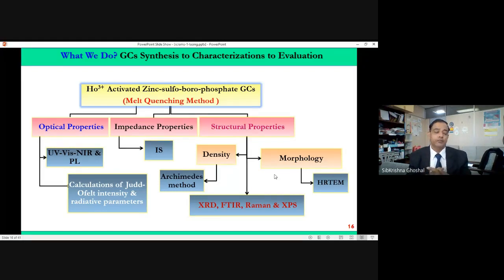So what characterization do we do on this kind of material? We do ultraviolet, visible, near infrared absorption spectroscopy, and photoluminescence spectroscopy, because this is needed for optical characterization. Then we do impedance spectroscopy for most of the dielectric measurement. Then we measure the density. Of course, density is important to calculate any properties of the material.